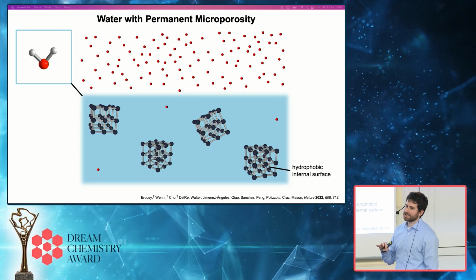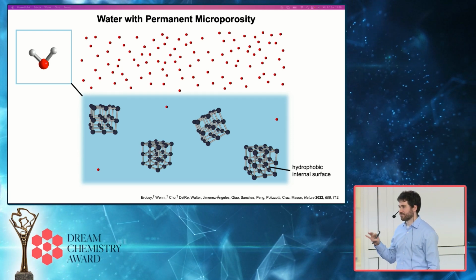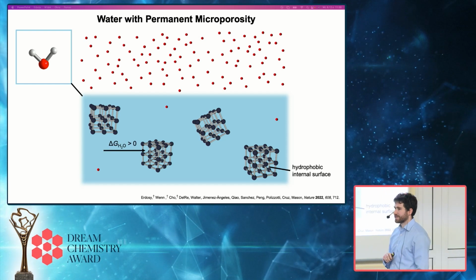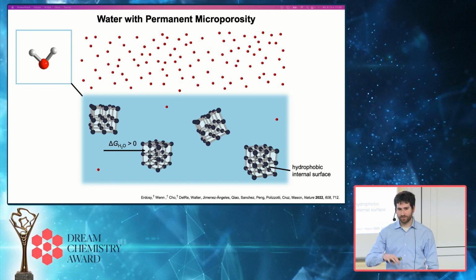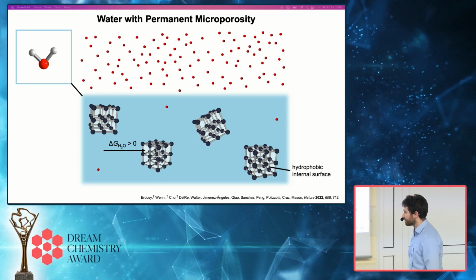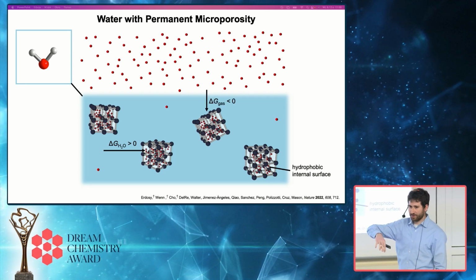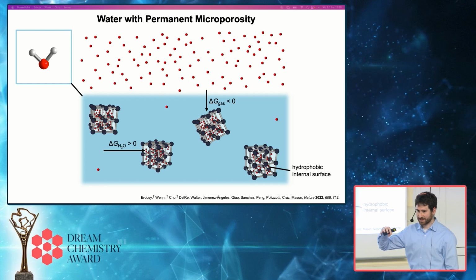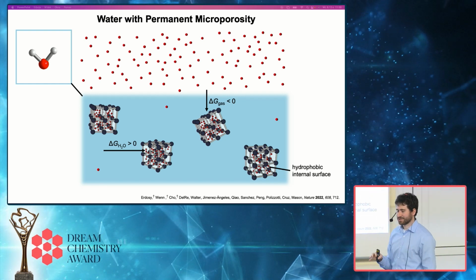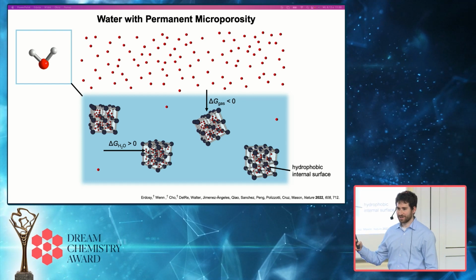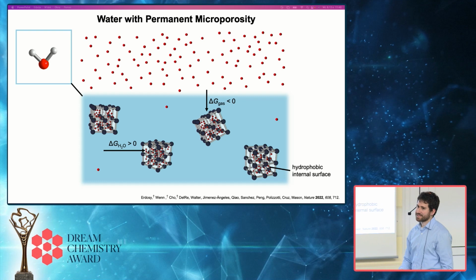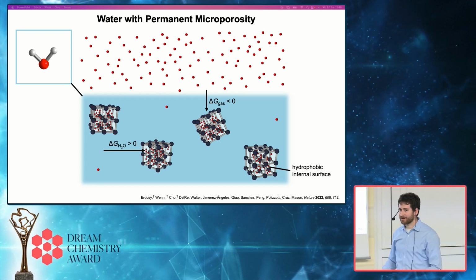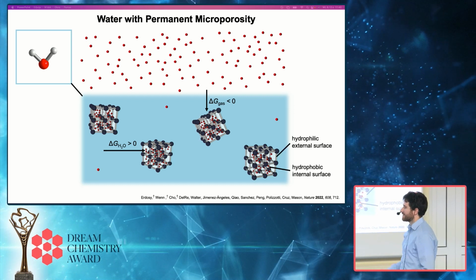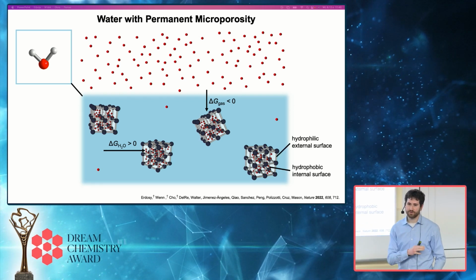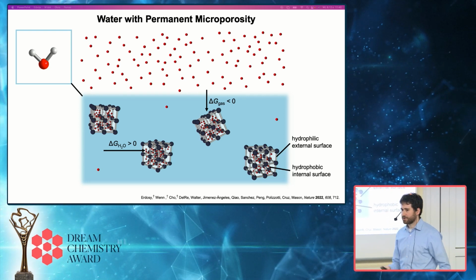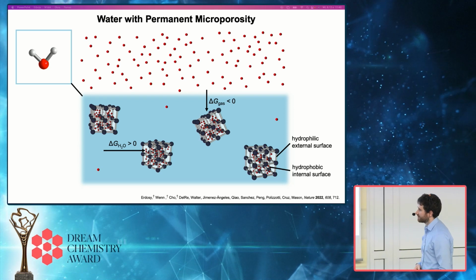And so in particular, what we wanted to do was to design microporous nanoparticles that had really hydrophobic internal surfaces such that it would be thermodynamically unfavorable for water, liquid water, to go inside the pores, just like in the two examples I just discussed. But it would remain thermodynamically favorable for gas molecules to go in the pores, and they would still be accessible to gases. The problem is if you take most hydrophobic materials and you try to disperse them in water, that usually doesn't work really well, right? They tend to clump up, aggregate, settle out of solution, and that's not going to be particularly useful for trying to actually transport a gas through water or make an artificial blood substitute or anything like that. So we wanted to make the external surfaces of these particles really hydrophilic so that you could form really nice uniform dispersions in water.